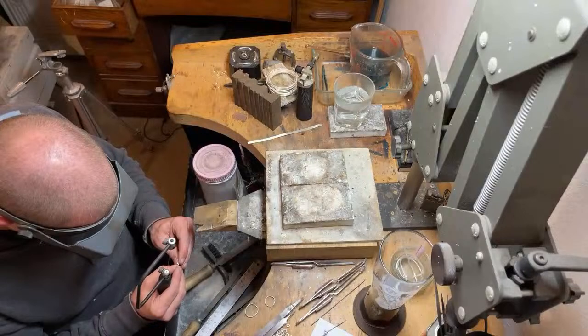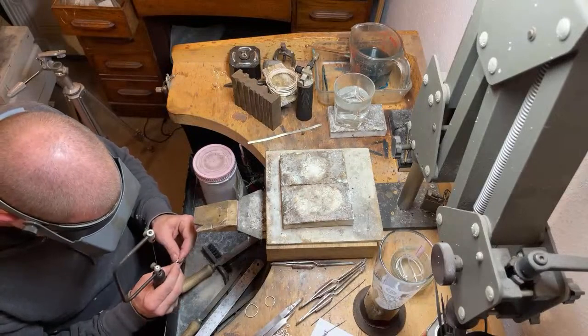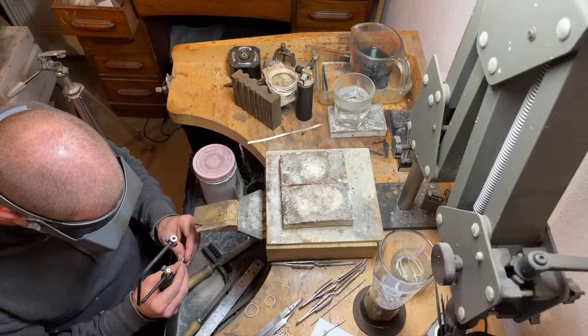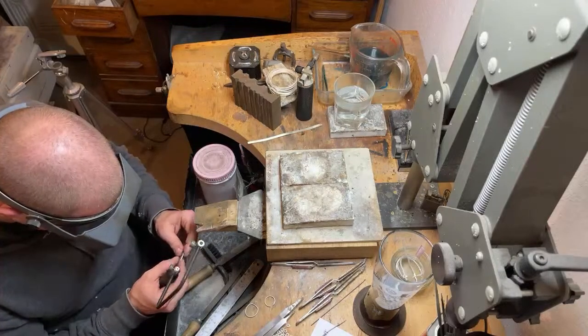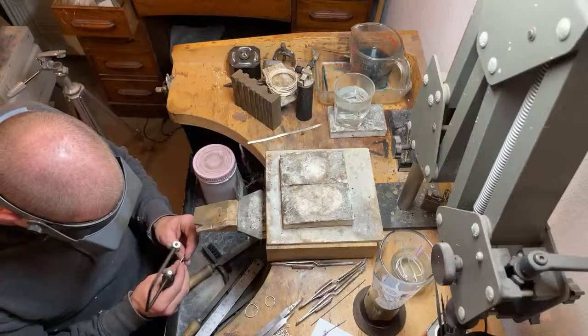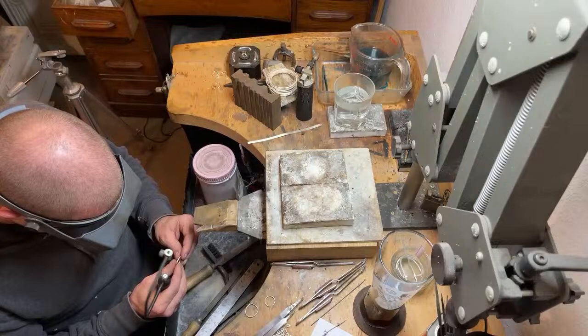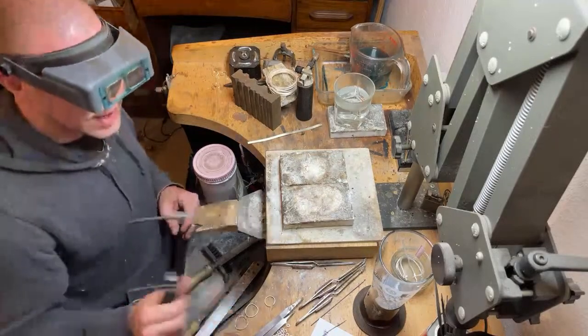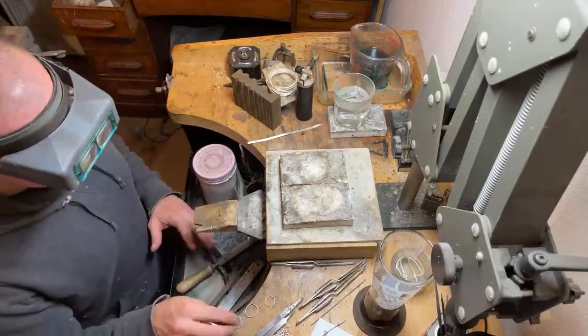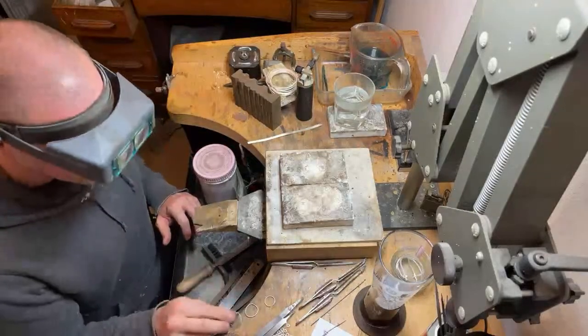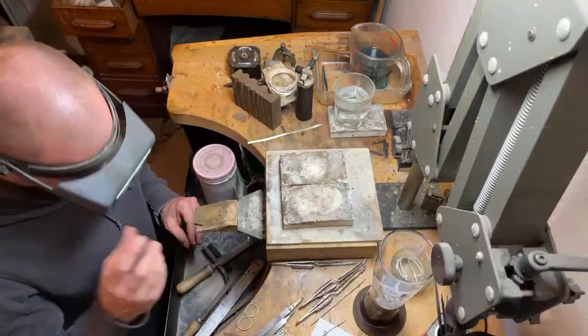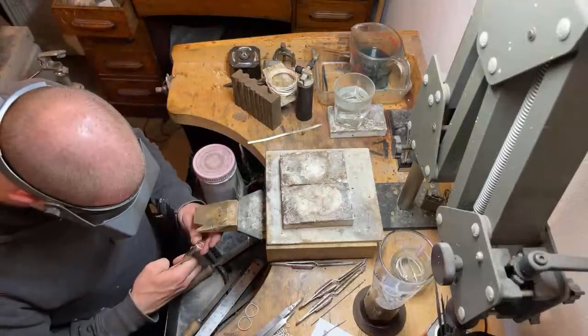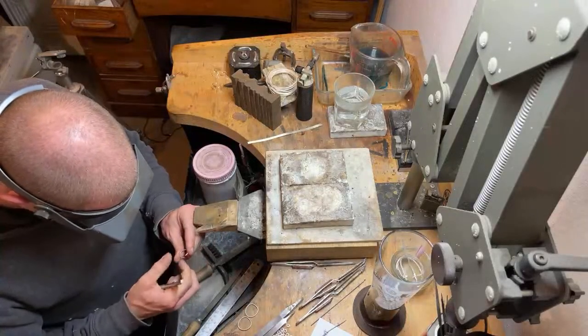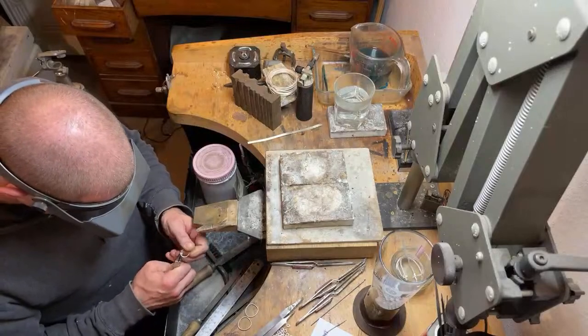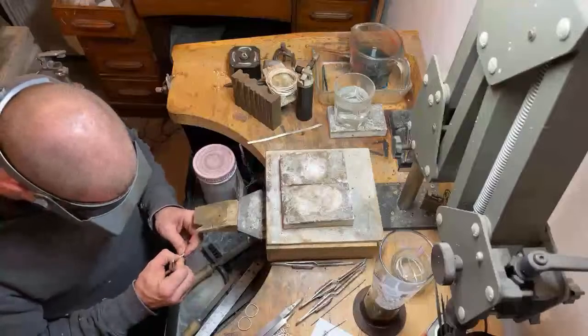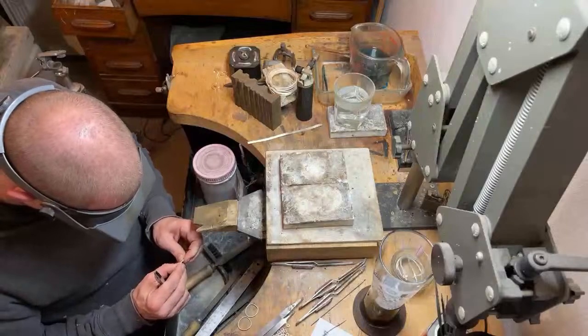And that's not just limited to not having a close fitting solder joint and using solder to fill the joint. It can also occur if you don't clean off the excess solder. If you end up with solder either side of the joint and you don't clean it off, you just polish it and it's still there, you'll get the same variation in colour. It's more pronounced if the ring's just held in stock for a long time, as opposed to if it's worn.